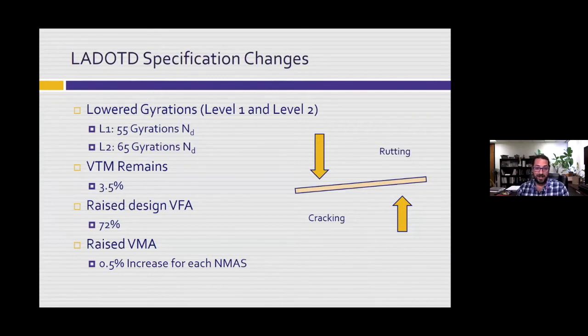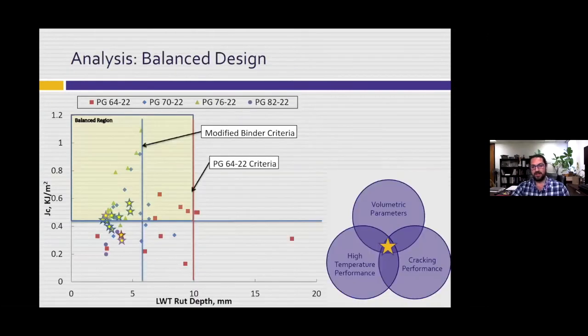I guess at the same time as implementing these two tests, we also did some volumetric changes to our specification. We lowered the gyrations from near 100 gyrations down to 55 and 65. Our air void content has always been 3.5% for at least the last three specifications. We raised the VFA from a minimum of 68 to 72, and we raised the VMA by 0.5%.